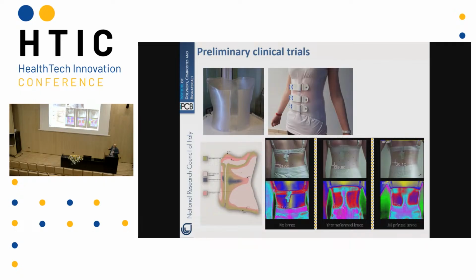These, for example, are results that we obtained with a clinical trial on a patient. We demonstrate that by 3D printing it is possible to obtain objects that can really be used on patients. It is a very simple geometry, just for a start. What we see is that this material has particular features, and we also cover the material with particular substances that avoid, for example, the formation of smell, because during use there is an increase in humidity inside. There is a formation of biofilm that starts to smell after some days, and also substances for thermoregulating the temperature on the body. The comparison between the commercial braces and those we obtain by 3D printing is completely different.